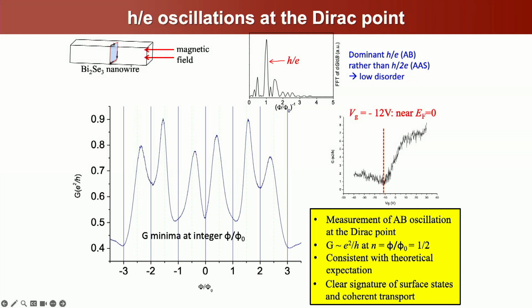And when I talk about phi over phi naught, this phi naught is determined by the area around the circumference of the nanowire. And so the fact that we have conductance oscillations as a function of phi over phi naught defined by the area of a hollow nanowire tells us that our conductance is in fact around the outside of the wire, not the inside. And so it's telling us that one, we have this high conductance, which is consistent with theoretical expectations, but also this is a clear signature of surface states. And what's nice about it, too, is that because we have to have a path in the top and bottom surfaces, it means that we have coherent surface states on the bottom surface as well as the top surface. And again, experimentally, this isn't totally obvious, because if you put a topological material just on a surface where it's now interacting with the surface, do you still have a surface state on the bottom? Theoretically, you do, but experimentally, that's not really known unless you measure something like this.